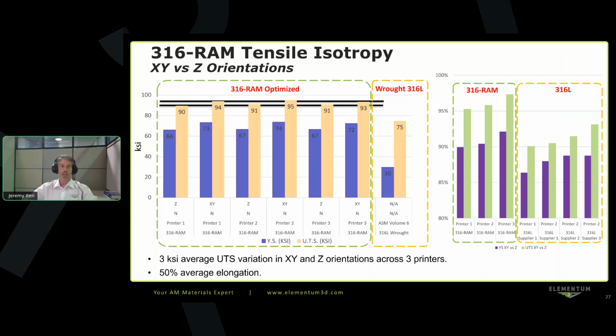So it wasn't to make it as high strength as possible in this case, but just make it easy to print. And you can see that the optimized RAM-based material compared to the wrought material, we're achieving better strengths and better properties than the wrought material. But compared to printed base alloy, we're also achieving much more consistent properties in the X, Y versus Z orientation. So on the right there, that's the difference between the X, Y, and Z orientation. And so the higher those bars are, the less the difference between the X, Y, and Z orientation. So the RAM material is much more consistent in all directions compared to the base 316L material.